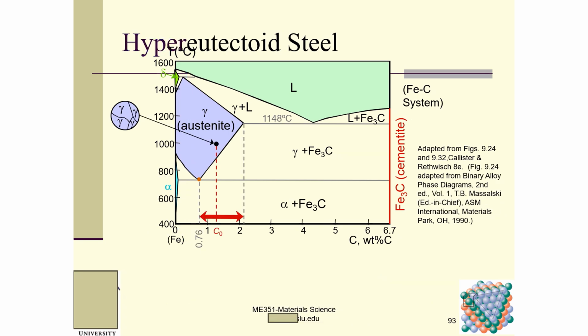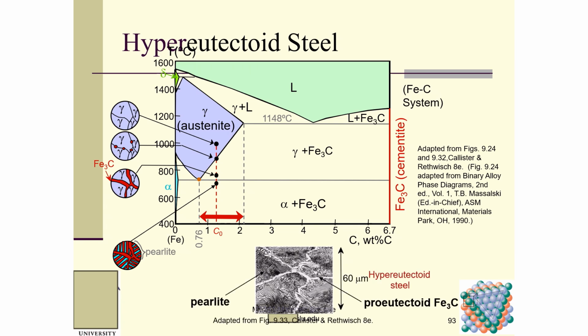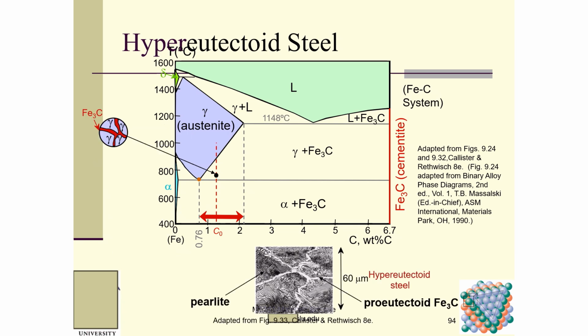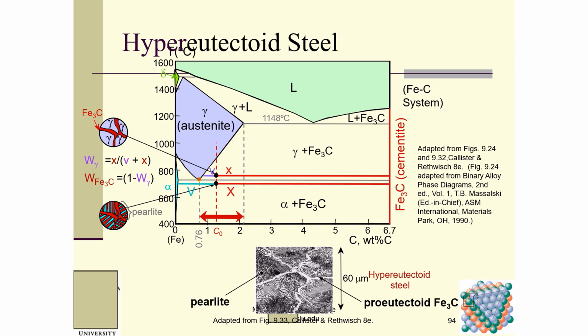And hyper-eutectoid means the composition of carbon is higher than the eutectoid composition, which is this value. You can see this gamma, and then we have cementite, Fe3C. Going down, we also have pearlite, this lamella of pearlite. This is a micrograph. Then we can use the lever rule to calculate the relative weight fractions. We still use this equation, and I want you guys to take a closer look at these equations.